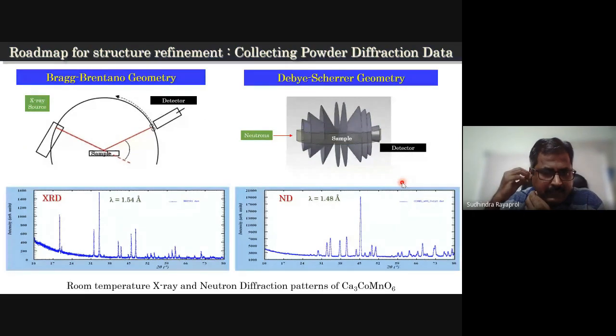Okay, now there are different types of geometries involved in the case of powder diffraction. This is a comparison for X-rays and neutrons. In the case of X-rays, we have what is called the Bragg-Brentano geometry, which works in the reflectance mode. What I mean is that you have an X-ray source and you have a sample. Since the X-ray cannot penetrate deep into the sample without being absorbed, it has more of a surface kind of behavior, meaning it gets scattered from the surface.